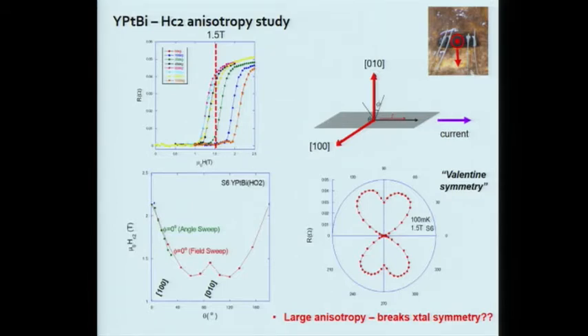And anyways, this is just a cut through here, for instance, to show that there's some anisotropy. But you can see the anisotropy here. Yes? Did you consider the demagnetization factors that may change the HC2 because of the crystal geometry? Yeah, I'm going to show you in the next slide. So when you see this, this is weird because this and this are identical directions. And we even did the experiment where we literally took the crystal and rotated it and did the same experiment, and it follows the rotation. It's the same.